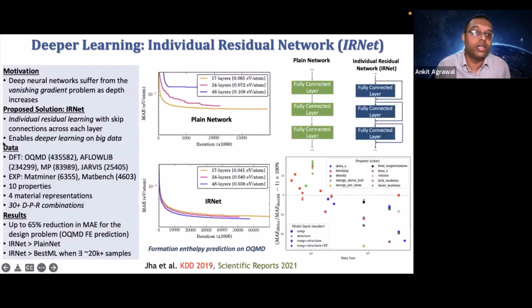The issue is that there is something called the vanishing gradient problem. The way these networks are trained is that the gradient of the error with respect to the weights is backpropagated to update the weights. So when the network is very deep, the gradients almost die out. They become close to zero, because these are very small numbers between 0 and 1. So when the network is too deep, then there is no more training.